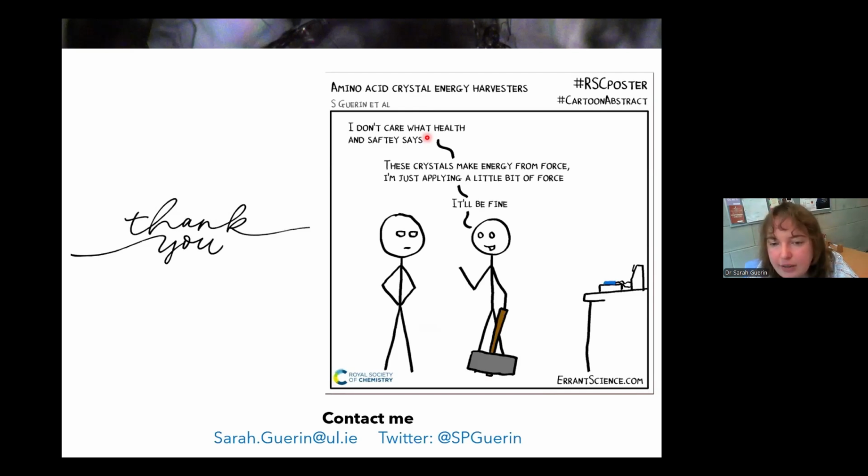In order to get your core piezoelectric constant, our picocoulomb per Newton value, you're dividing your polarization tensor by your elastic stiffness. So that's why I was saying that your piezoelectricity is inversely proportional to the flexibility of the material, or the more compliant a material is, the more piezoelectric it's going to be.